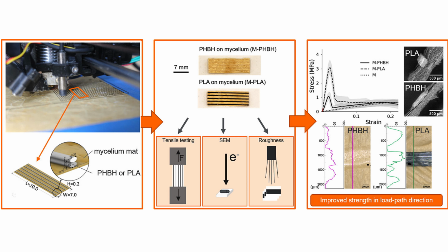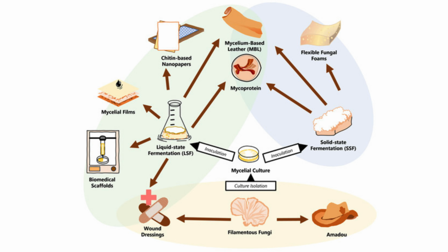In addition, the wearability and resilience of the biogenic leather substitute to perspiration, water spotting, solvent wicking, crocking, UV exposure, and salty water have also been noted to be enhanced by hybridization with other natural or synthetic materials, such as felted polyester reinforcement or polylactic acid surface coating. The post-treatment processes are mainly to improve the aesthetics of the material, and they involve large-scale modifications of appearance, which can be achieved through techniques such as carving, imprinting, embossing, stamping, and dyeing of the mats.